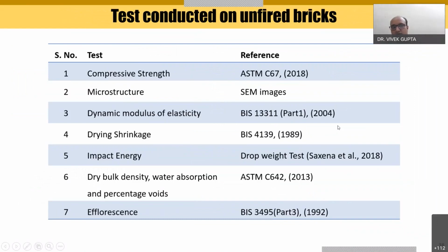It may vary based on the raw materials, but the same methodology can be implemented for the respective raw materials. Then we have chosen a particular binder ratio based on our compressive strength requirement. Like we have targeted 10 MPa, which is the required compressive strength as per the CPWD norms for building bricks. So we have prepared these 10 mixes based on the 5 different moisture contents and 2 mixing sequences. And then we have conducted these different tests.